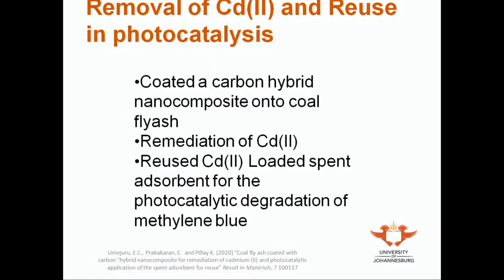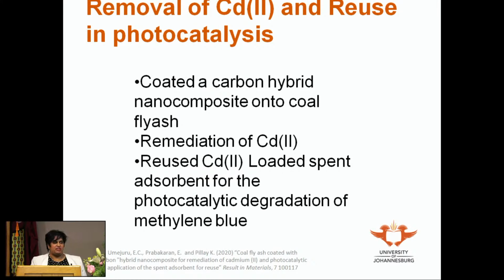Okay, so we've tested the pollutant-loaded spent adsorbents for a number of applications. Unfortunately, I'm restricted with time this evening, so I'm only going to tell you about two such studies. The first of these was a study where we coated a carbon hybrid nanocomposite material onto coal fly ash, and we used that for cadmium-2 removal. And then we attempted reusing the cadmium-2 loaded spent adsorbent in a photocatalytic application, where we studied its potential to photocatalytically break down methylene blue dye.